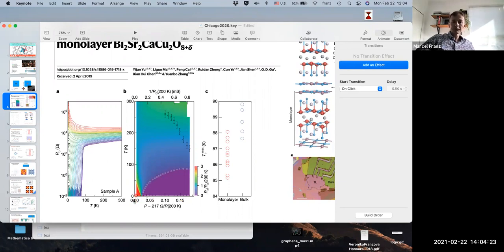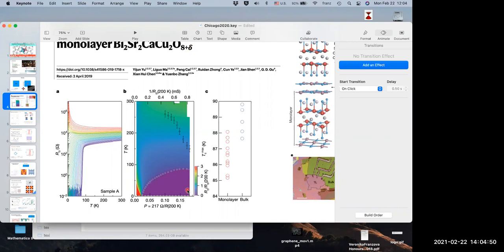Instead, it's an antiferromagnetic insulator, and at around 0.02 in these units, which is this parameter delta here, which is the doping, it starts to superconduct, and the optimally doped situation is around this doping, 0.17 or something. So is that in real bilayer graphene?